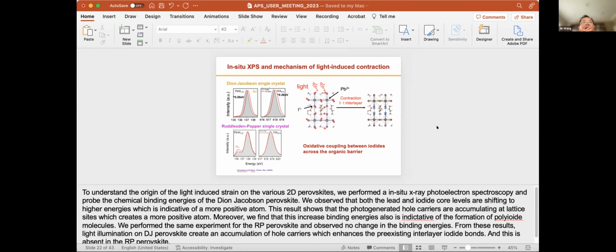Or is it more homogeneous throughout? So we think that this effect is homogeneous across the sample for multiple reasons. We've done these measurements on powders, which are almost transparent. So you basically have all the x-rays going through. You can also get a signature from the substrate, and the light actually penetrates through, so you can measure the transmission of the light. We've also performed these on single crystals, where the flakes are of the order of about 200 nanometers of thickness, and this also shows the effect. And then, of course, the solar cell films, which are about 200 nanometers, right? And all of these things seem to show the same effect, this light-induced contraction.